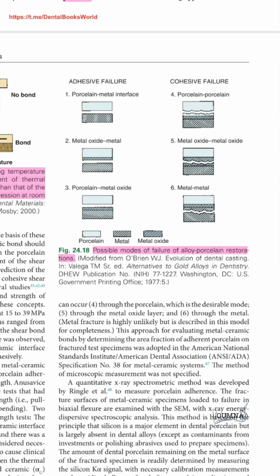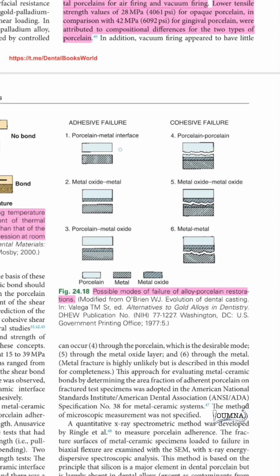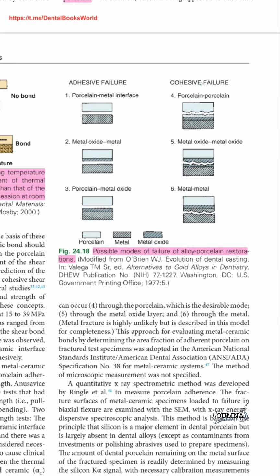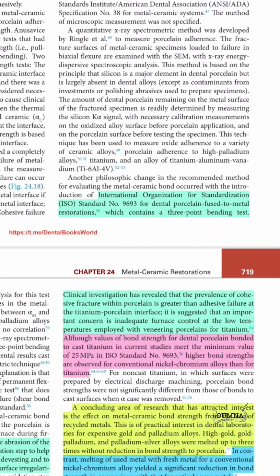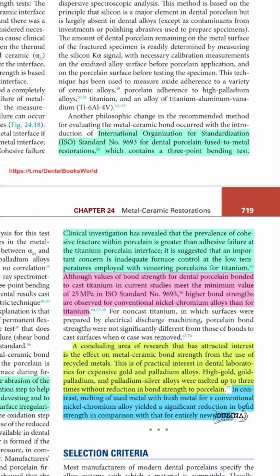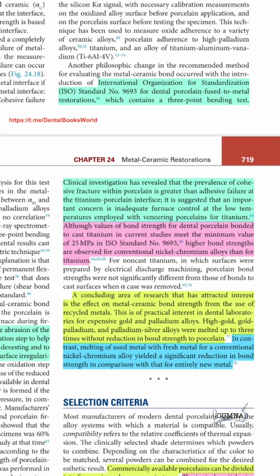These are the possible modes of failure. It can be attributed to the metal oxide layer, or between the metal and the metal oxide itself, or between the porcelain and itself. They are saying that the cohesive fracture within porcelain is greater than the adhesive failure at the titanium porcelain interface. And the reason for the fracture in the porcelain is inadequate furnace control.